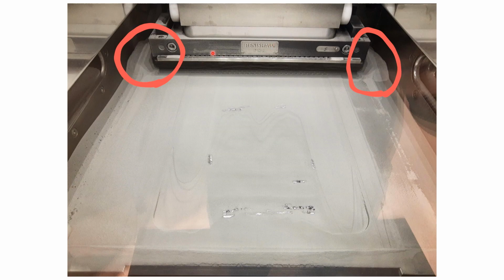But what's happened overnight is the overflow system of the machine has filled up, leading to an accumulation of powder in the corners of the machine here, which has prevented the mechanical dosing action of the machine. It needs to push on these plungers here in order to dose powder out of the hopper. So the machine, while it still has powder in here, hasn't been able to actually dose powder correctly. So we've had a failure, and we could argue that maybe this is down to human error, that the operator shouldn't have let the overflows fill up overnight. Of course, that's easier said than done. Or we could look to the future and say more modern machines in a more advanced state of evolution will automatically recirculate powder, and failures like this will become rare.